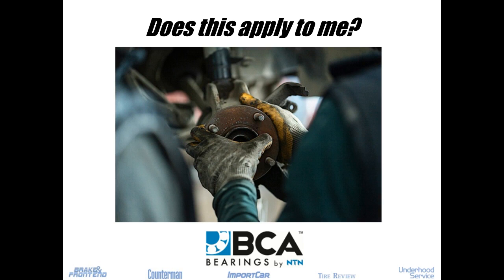This is Mark Tarrant again. I'll take that question. In automotive applications specifically, we want to use polymer cages. It's a very special polymer that is a low friction and high heat resistance material. When you're dealing with a metal cage, which is used in more industrial applications at times, you're introducing more metal on metal contact than is necessary. Even though there is grease lubricating, you want to cut down on metal contact. So long story short, polymer is superior in automotive applications.